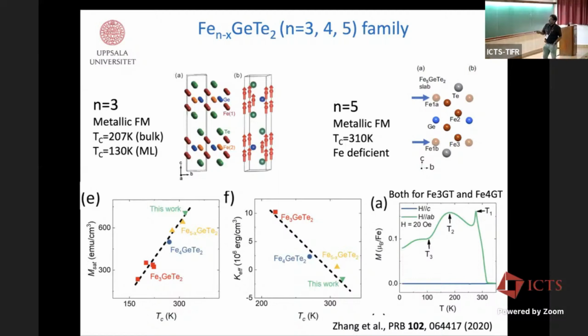For Fe4 and Fe5, you see there's a peculiar behavior of magnetization versus temperature. At low temperature, you have a rather low magnetization, then it pops up, and then there are some characteristic temperatures you can see. And then finally, after T1, it goes to the paramagnetic state. Now, as far as I know, this behavior has not been understood properly. Why is the low temperature behavior like this? People have conjectured that there can be some helimagnetic order, complex magnetism, things like that. So this part is still under open discussion.